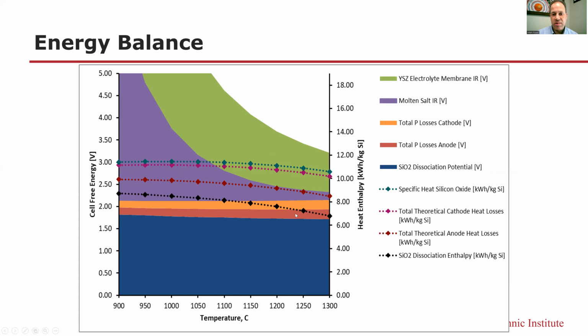So the thermal energy absorbed includes the enthalpy of the reduction, which is above the dissociation potential, plus the minimum theoretical anode and cathode heat losses and the specific heat of heating the silica to this temperature. So as long as we're generating more heat than we consume, then we can lose some heat through the sides and we stay in thermal balance.